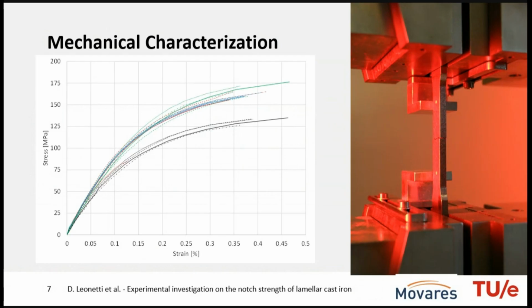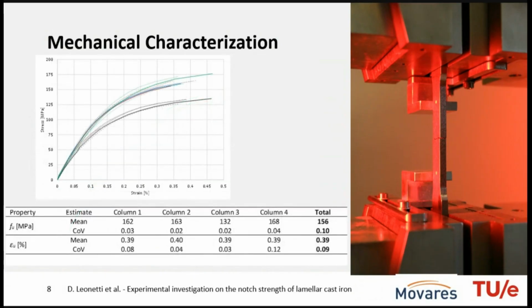Within one column, the material behaves pretty much uniformly, but there could be quite some scatter from column to column. It's very dominant, although this was the same foundry that produced this material back in the time. So, just to summarize what I just mentioned about the variability of, for example, the ultimate tensile strength, within batch variability and in between batch variability.